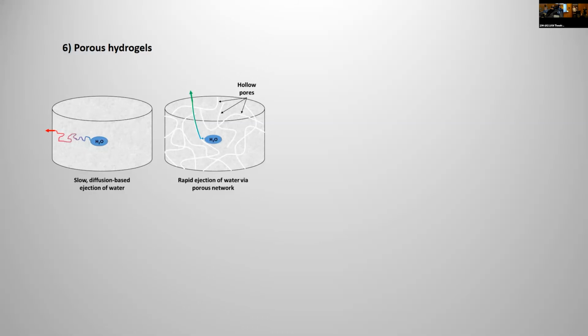And the other strange effect that we found when we were doing this is the very outside shell of the gel would be a lot harder or drier. So if you don't have these pores in it, sometimes you'd see these bubbles forming just under the surface, and you just want the water to get out so it can function as a material, but it just wants to stay there as annoying little bubbles.